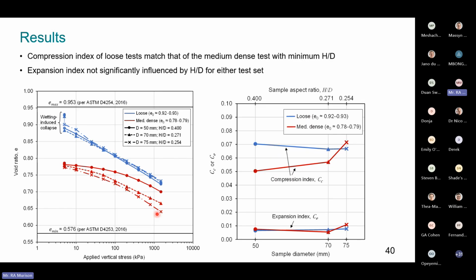So if we plot all of these on the same set of axes, we see that the 75 millimeter medium dense sample seems to have a normal consolidation line that's approximately parallel to that of the three loose samples. And we can see that here as well if we compare the compression index to the compression indices of the three loose samples. So that then seems to conform with the framework that we developed earlier. For both sets of tests, the expansion index was not significantly influenced by sample aspect ratio.